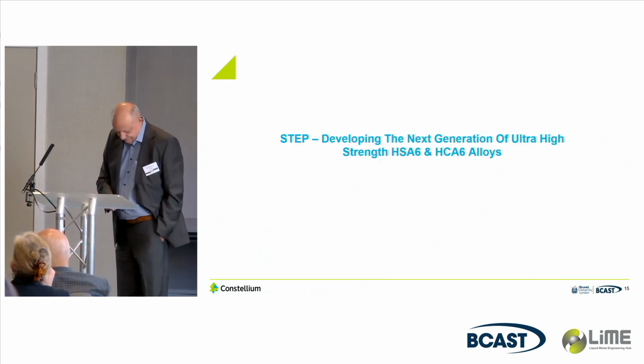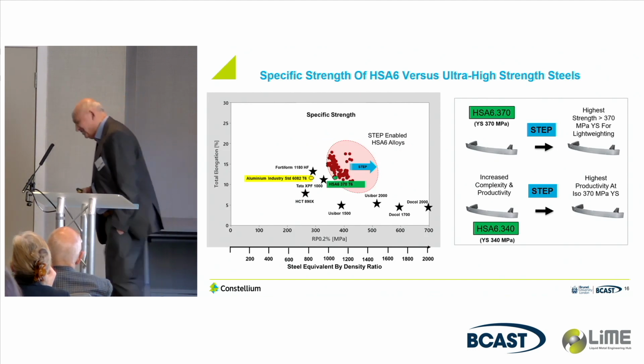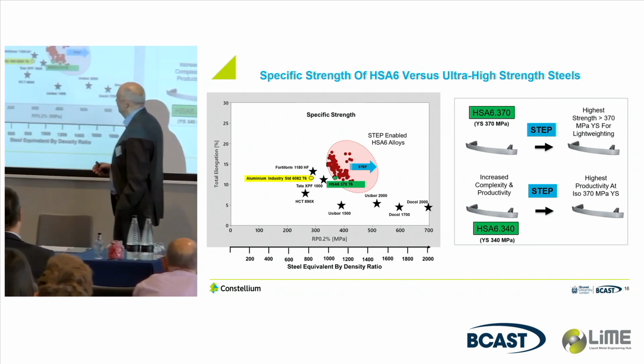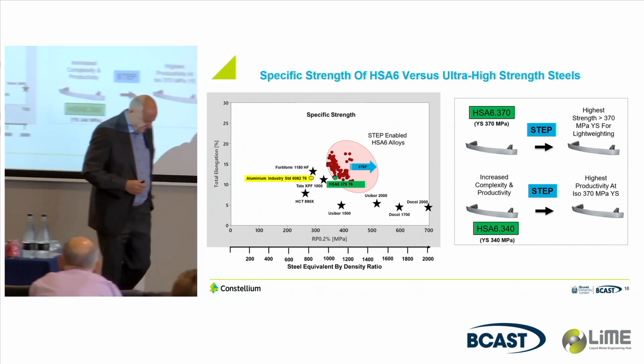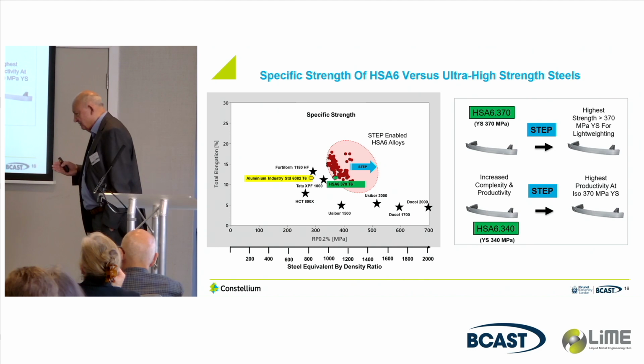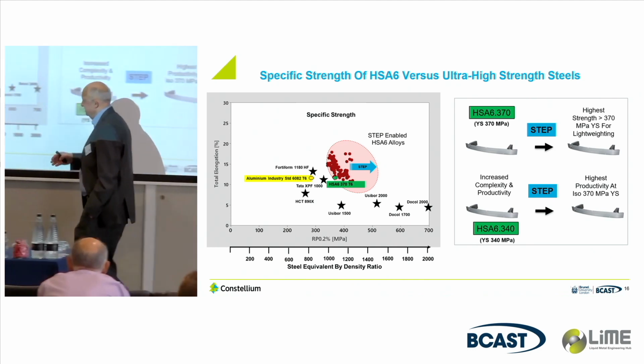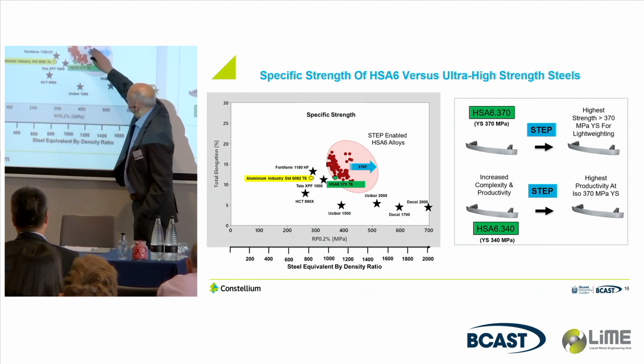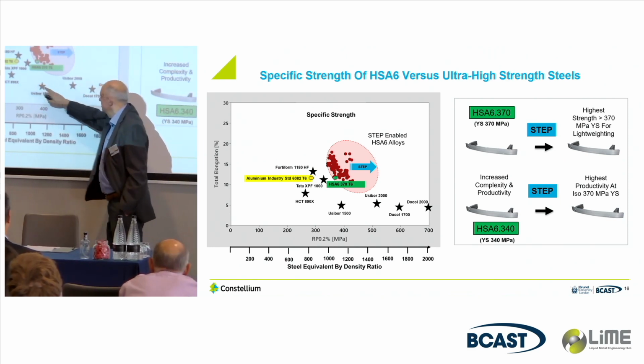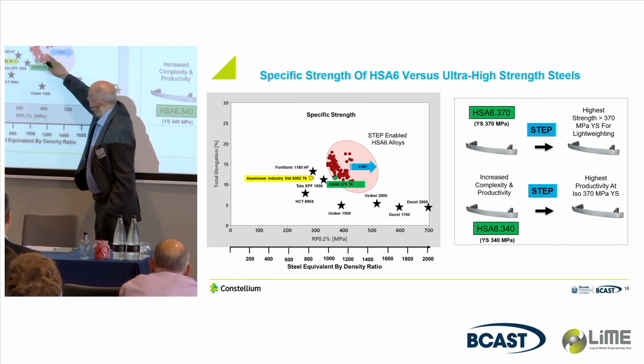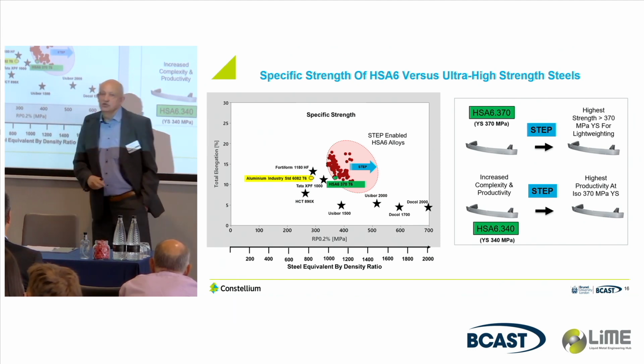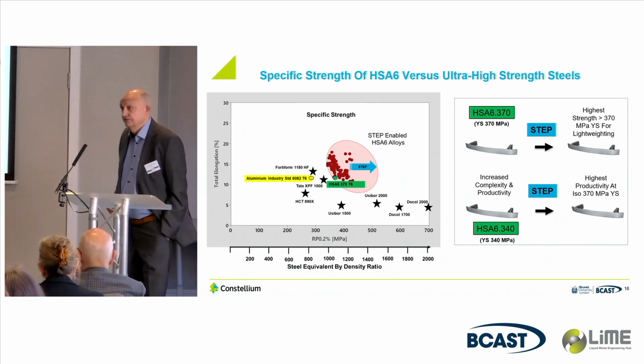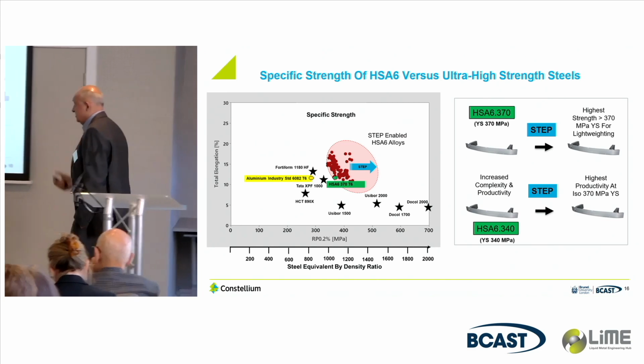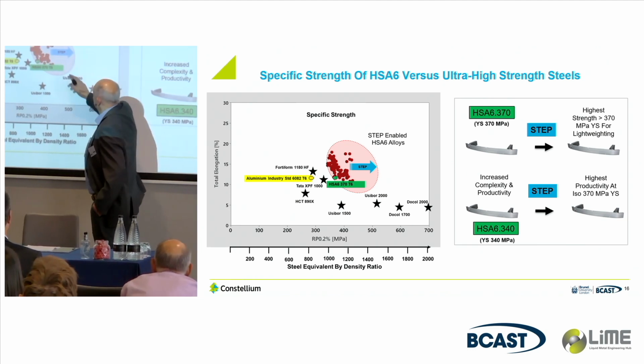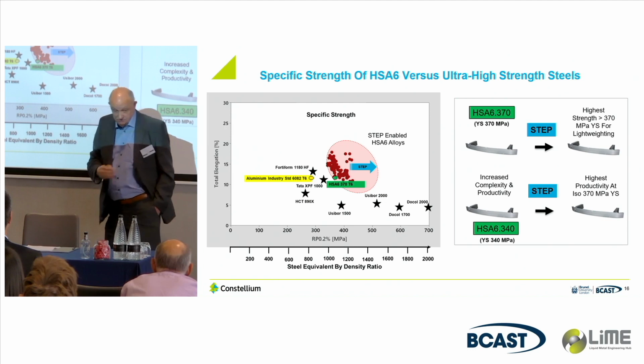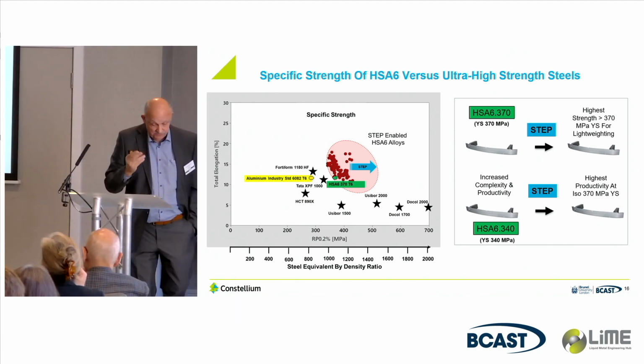So, what about STEP? Well, Professor Fan obviously borrowed one of my slides. You've seen this one before. What this is basically showing is the relationship. This is a specific strength relationship, so we've obviously got to divide it through by the density. This shows what this means in terms of STEP versus these ultra high strength steels. And you can see actually where STEP is starting to get close to these generation 3 steels. So what we're trying to do is to move that to the right, this way, and try and keep the ductility up as far as we can, and you can see why that system.